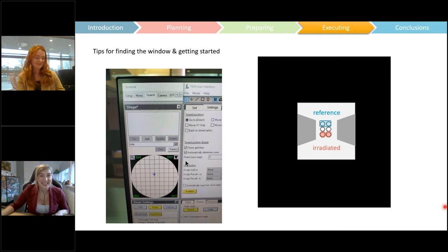Another question that's come in is the silica contamination specific to your experiment, or is it more general and originates from the chips themselves? It originates from the chips itself. So this is what I mean about it having been confirmed by other universities. They did these experiments, and so did we actually, on chips with no sample, and we see the same effect. It is a water plus silicon nitride plus beam effect. It's made worse by working at low pressures.